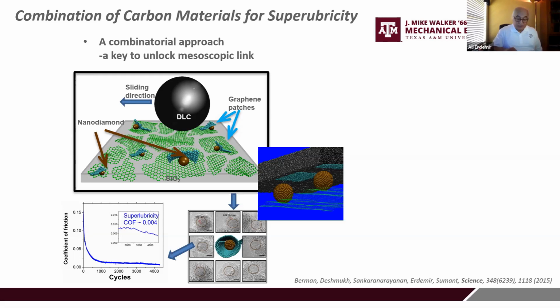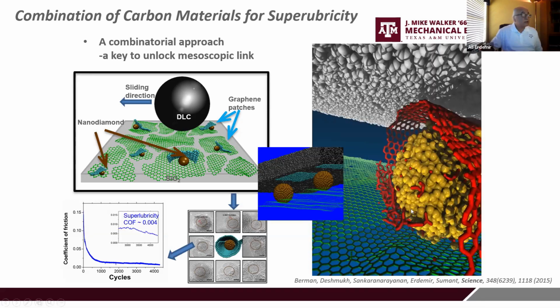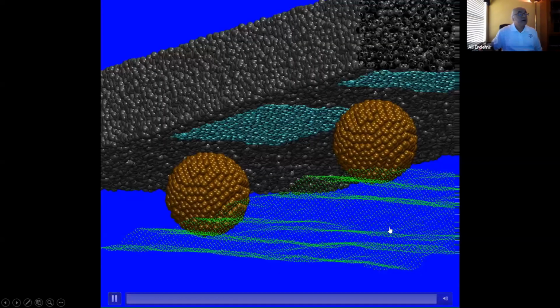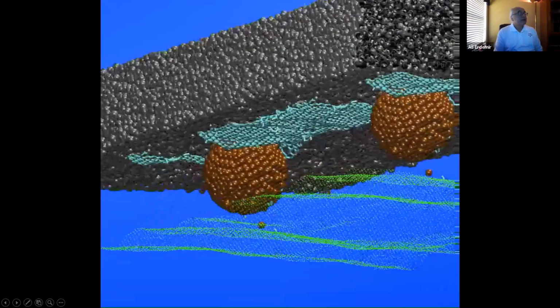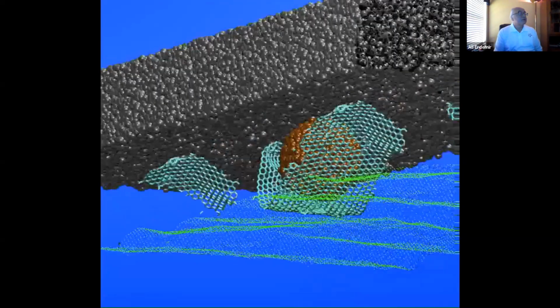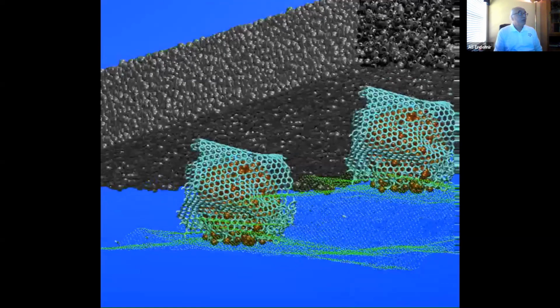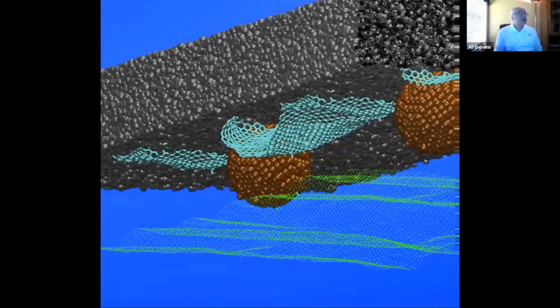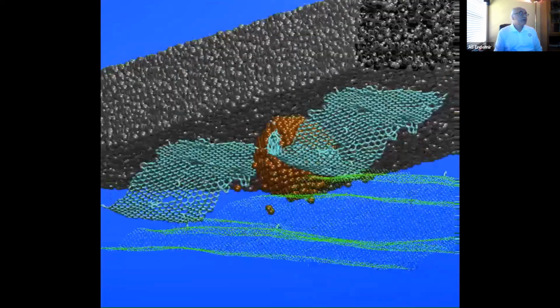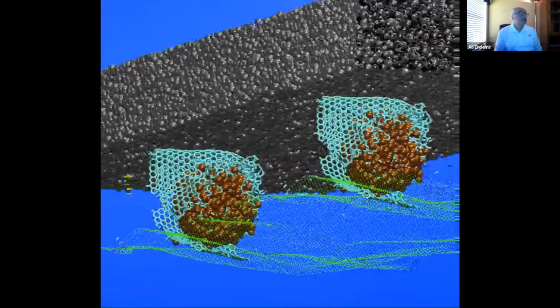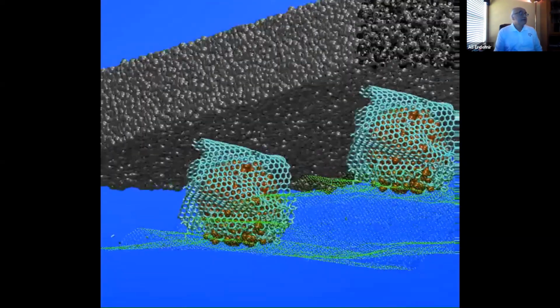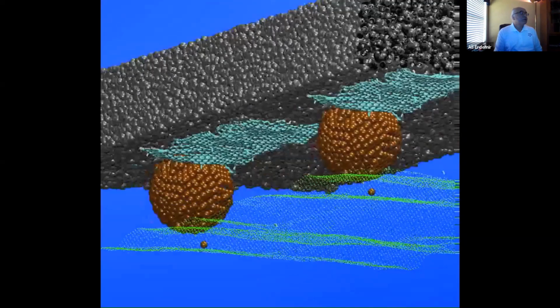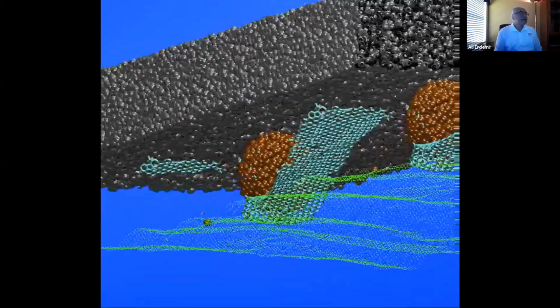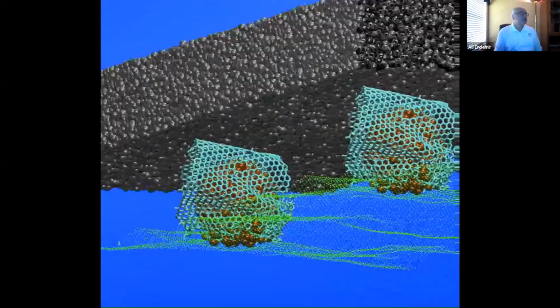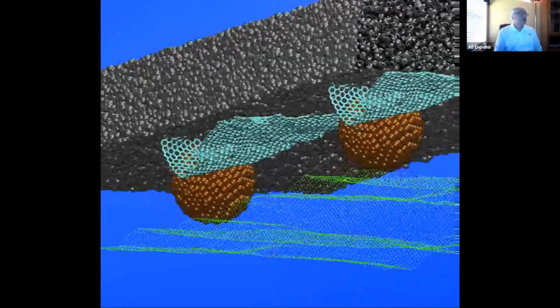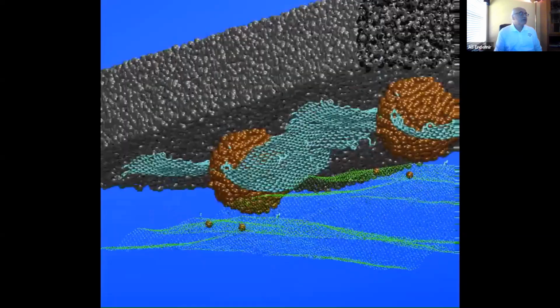This was also simulated using reactive MD simulation methods that show exactly how these nanoscrolls form. Once the nanoscroll forms, the severity of the nanodiamond as an abrasive and adhesive particle has been diminished, so they became more benign and could also roll, in addition to having this surface-to-surface interaction, or what we call a commensurate state of contact.